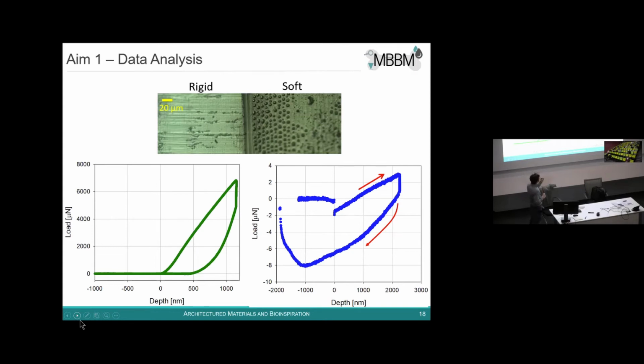So there are some pores in the soft materials, but I don't think those blisters are caused by the pores. I think these are also caused by the cryosectioning. But the problem is that we didn't see these everywhere. They seem to be localized close to the interface. So when we indented, we made sure to try to avoid these as much as possible. But we also indented in those blisters, and we didn't see big differences in terms of behavior. So we said, okay, we are still fine. There is another picture where I think the presence of those is less dramatic. Yeah, but it's a good point.